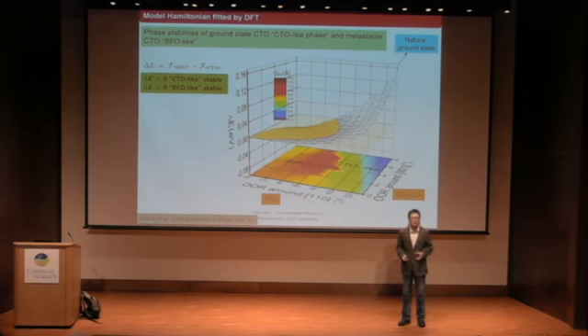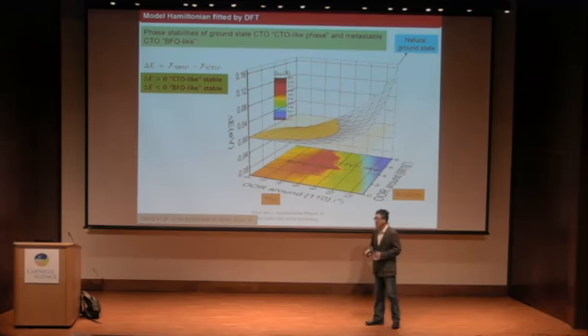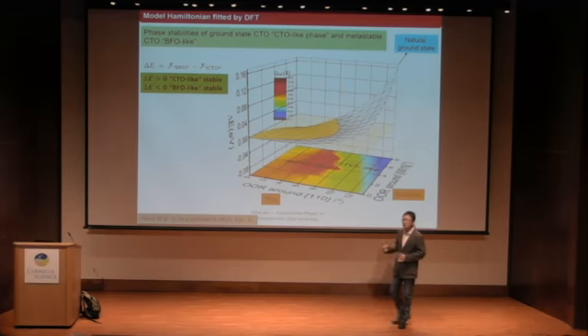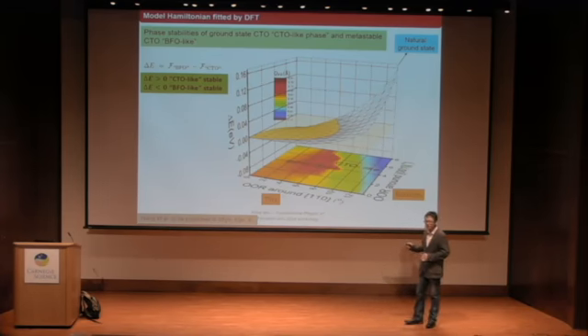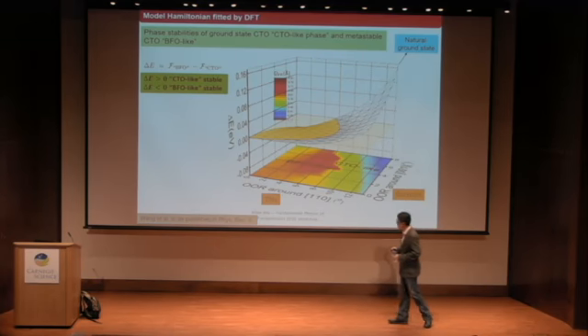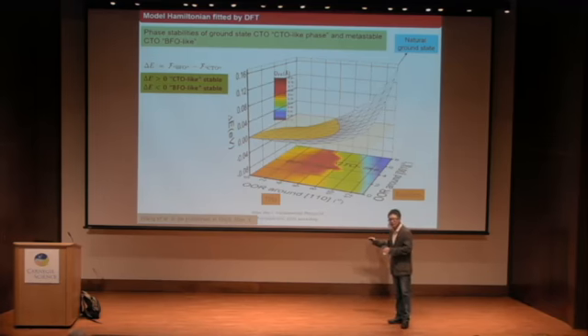Then how do we plot rotations as an order parameter? So in-phase rotation and out-of-phase rotation have the same order parameter. Now what happens is, when the rotation and tilt are suppressed, in particular the tilting was suppressed moderately, we gradually move into this region. In the plot, we also project colors to represent the amplitude of the ferroelectric mode.